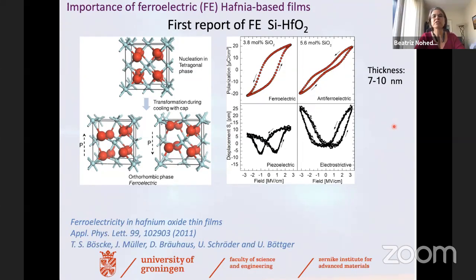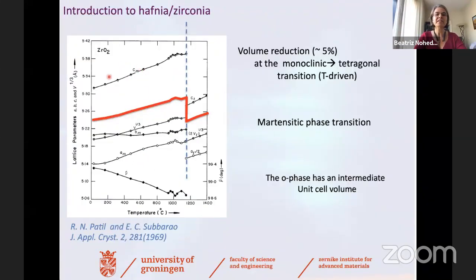So there were a lot of questions about what exactly are the factors that determine the appearance of ferroelectricity in these materials. And after a lot of work by many different groups, it was clearly demonstrated that in order to achieve this ferroelectric phase, one needs to start nucleating or stabilizing the tetragonal phase of hafnia. If one goes to the ground state of the material, which is a monoclinic phase, it is not possible to reach this ferroelectric phase. So there is a transformation needed from a tetragonal phase to this orthorhombic ferroelectric phase in hafnia. In some cases, this could happen during capping or confining the material. In some cases, during doping, in some cases, you needed both.